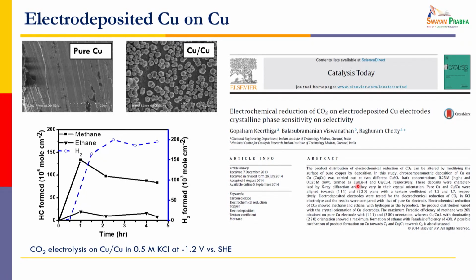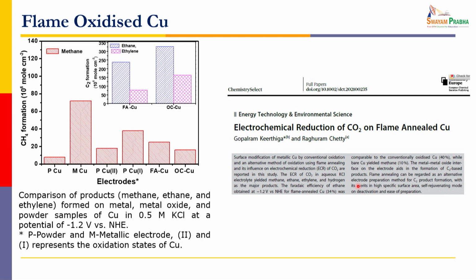And the blue one you see is hydrogen. So we have more hydrogen as well, because hydrogen is a byproduct which we cannot avoid in aqueous solution. So that's something which formed. What we found was, when you deposit more and more copper, you are able to increase the methane selectivity. So that's converting carbon dioxide into methane. Similarly, when you have a mixture of metal and an oxide, your selectivity is slightly higher. So that's something we found out.